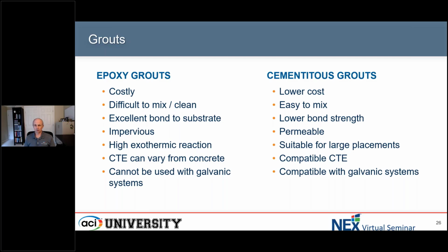The other downside to epoxy grouts is that they typically cannot be used in conjunction with galvanic systems, because these grouts are completely non-conductive, and galvanic systems do rely on some conductivity of the grout in order to properly function. So generally you won't see epoxy grouts used in galvanic type systems.